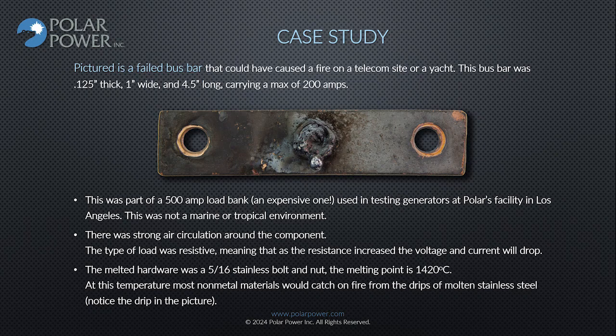There was strong air circulation around the component. The type of load was resistive, meaning that as the resistance increased, the voltage and current will drop. The melted hardware was a 5/16 stainless bolt and nut. The melting point is 1420 degrees Celsius. At this temperature, most non-metal materials would catch on fire from the drips of molten stainless steel. Notice the drip in the picture.